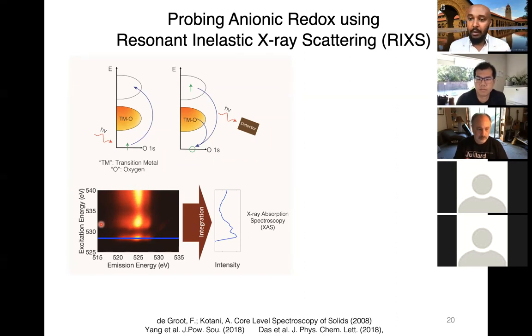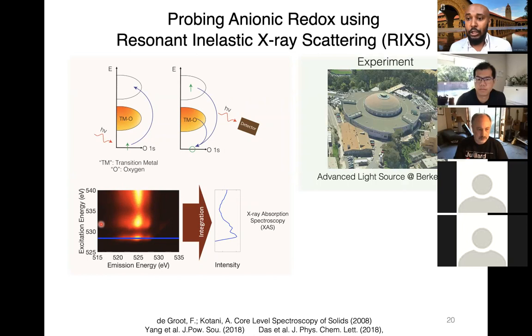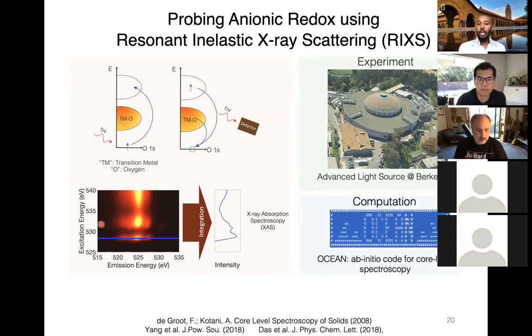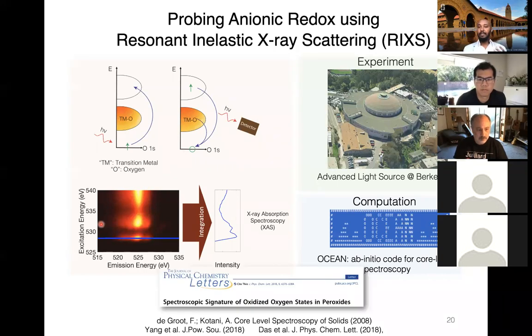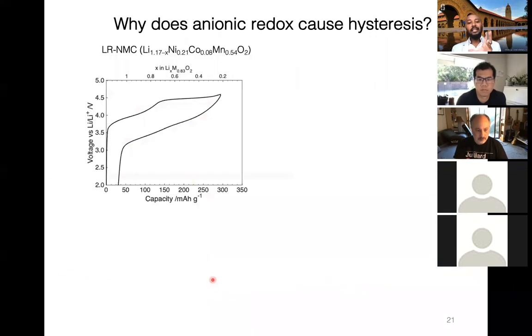So we perform this RIX measurement at the Advanced Light Source at Berkeley, and we complement this experimental result with computation using a first-principles code for core-level spectroscopy called OCEAN. And you can learn more about the accuracy of this method to study oxide systems in our recent paper shown over here. So using this RIX technique to understand the properties of this lithium-rich NMC material that I introduced a couple of slides ago.